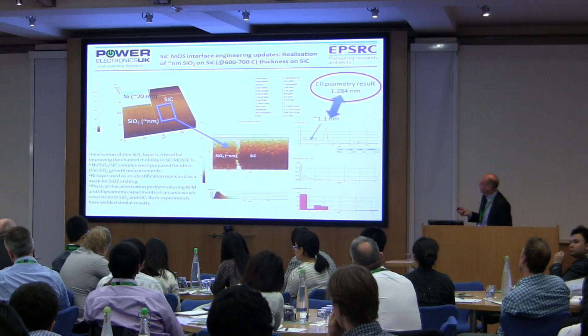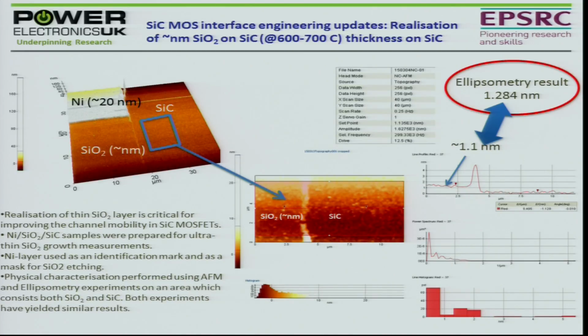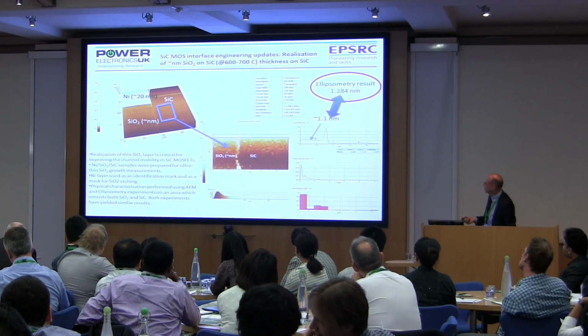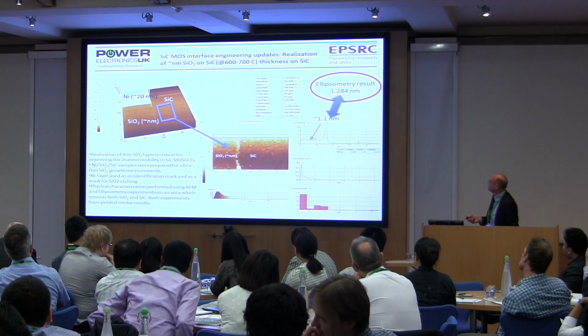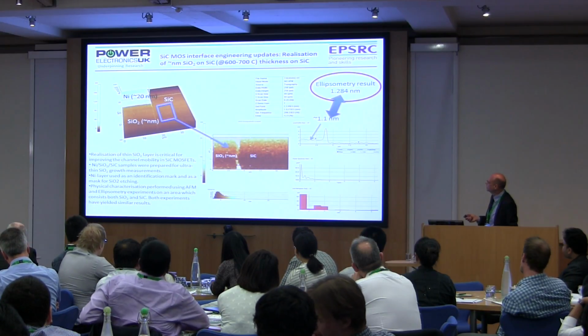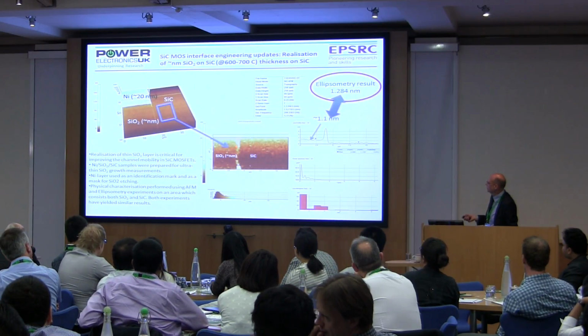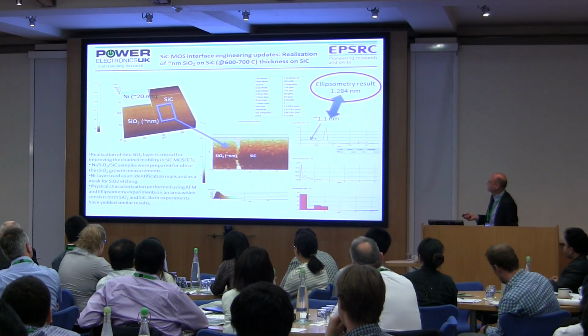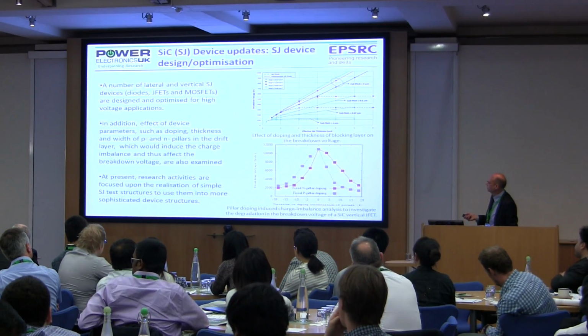This shows some work that they have been doing, some measurements trying to look at this interface between silicon dioxide and silicon carbide, and looking at the defects or the material that's here. You always get some sort of graded layer there, which is neither silicon dioxide nor silicon carbide, but a mixture of the two. And they've been probing that interface to look at what's there, because obviously we don't want that there. And so if we can remove it, brilliant.